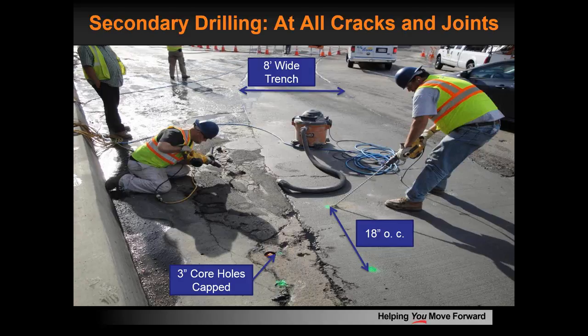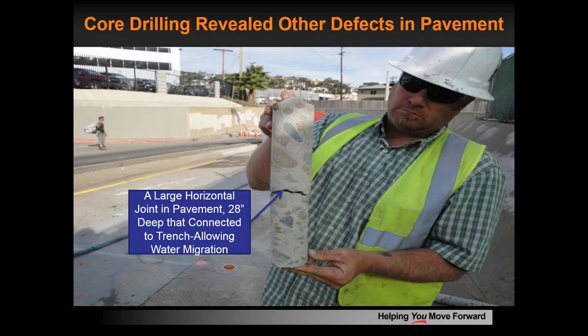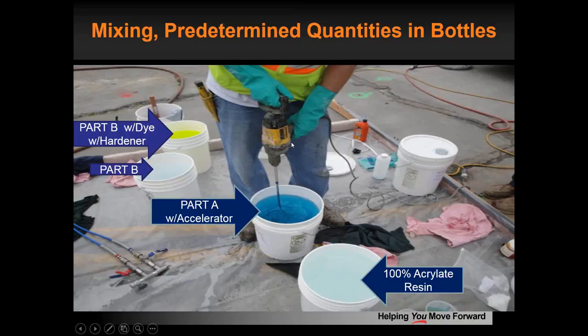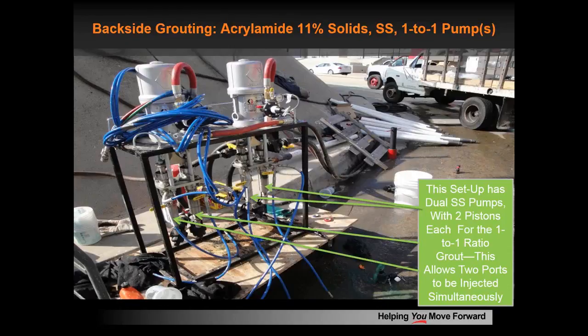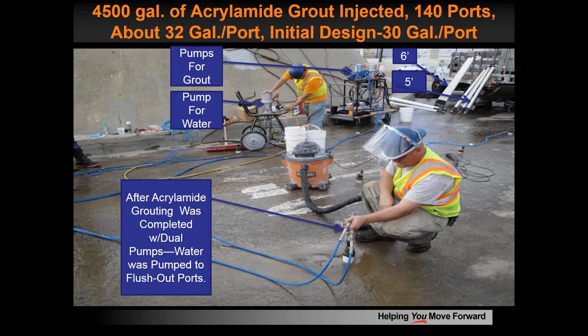a real concentrated solution of acrylamide. Here's a core that we took out of that area where they actually took 28 inches of concrete off the top, put a membrane, and then, as I said, that lasted about 5 to 7 years, and then it re-leaked. Here we are mixing up some of the acrylic resin. These are the pumps. These are piston-driven, one-to-one pumps that I use. Many times we'll pump 2 ports at a time, and I got these 2 pumps in unison.